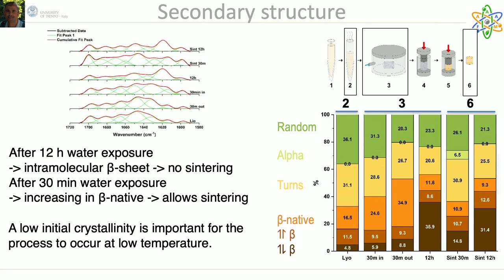This analysis permitted us to confirm that a low initial crystallinity is crucial for the process to occur at low temperature, and that the presence of water is capable of plasticizing fibroin, permitting the thermal reflow. However, since water is responsible for triggering the transition to beta structures, the sintering has to be performed before the transition occurs, and possibly with fast ramp time, as previously evidenced by transparency.